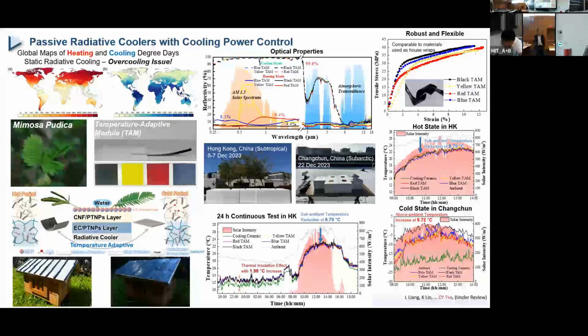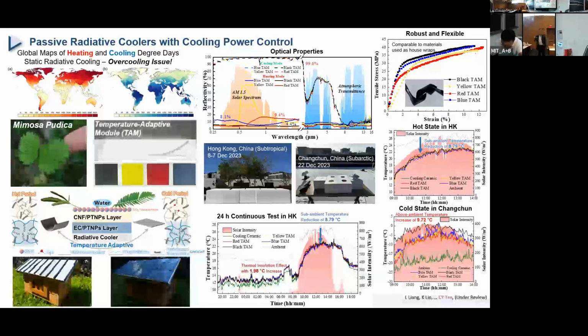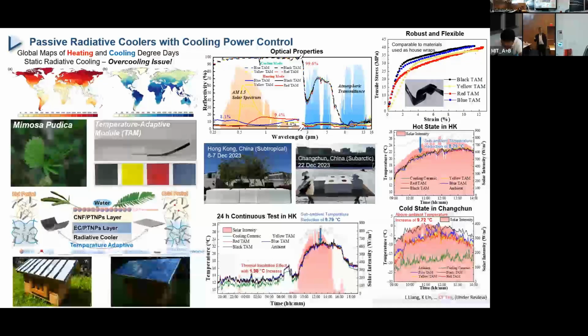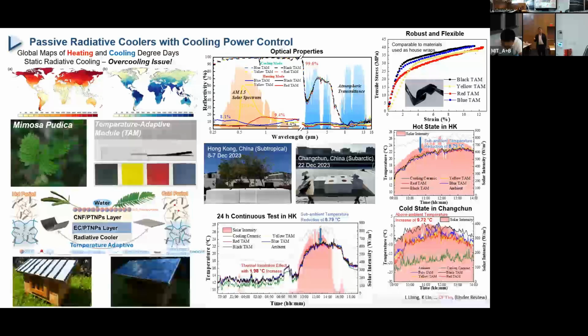We have demonstrated that this kind of coating is also flexible, and we have conducted a few tests. In Hong Kong in summer, we can reduce the temperature about 9 degrees Celsius below ambient. Then we went to Changchun, a northern city in China, where the coating is about 9 degrees Celsius higher than the ambient, which can perform the normal heating function.